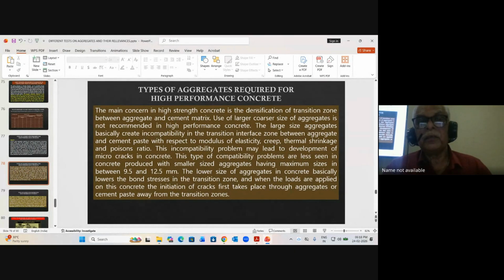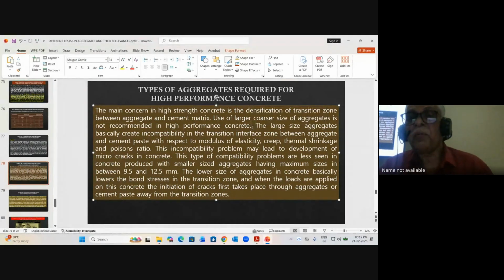So what happens? Use of coarser size aggregate is not recommended in high strength concrete. Larger coarse size is not recommended. Higher size of aggregates is not recommended in high strength and high performance concrete, because larger size aggregate basically creates incompatibility in the transition interface zone between aggregate and cement paste, with respect to modulus of elasticity, creep, shrinkage rate, and Poisson's ratio.